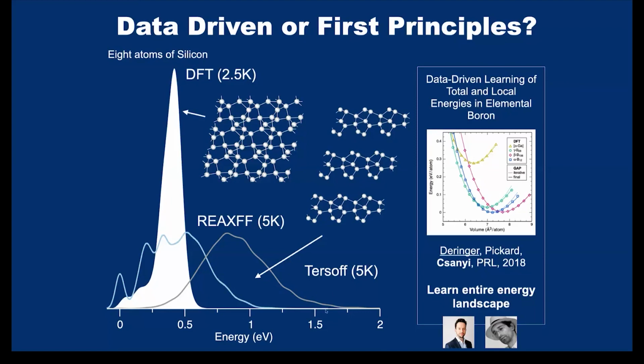So this failure of the Tersoff potential to describe the whole energy landscape would mean that actually random sampling would fail. You'll spend most of your time in the peak of the distribution here, which are made up structures. They're not real silicon structures. They're false structures. They don't appear in a DFT search. And there is a small probability, but a very small probability, of arriving in the diamond structure. Whereas in the case of the DFT, there's quite a reasonable probability of arriving in the diamond structure.